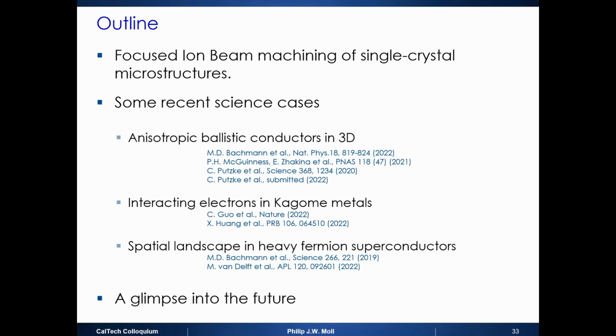In the last part, I wanted to talk about heavy fermions, strong correlations, and heavy fermion superconductors, essentially. Here, the question is whether you can take a single crystal of, say, a heavy fermion, and imprint a tailored strain field in it. You don't do uniaxial pressure. This is done a lot, but you really do a very, very complicated strain field. That strain is position-dependent within the device. And if TC is a function of the strain, you might get very interesting landscapes of TC. Now you could say, well, if you just plastically deform it, you get crazy landscapes of TC. Yes, that's true. But if you deform it in the right way, you might actually get interesting landscapes in TC.